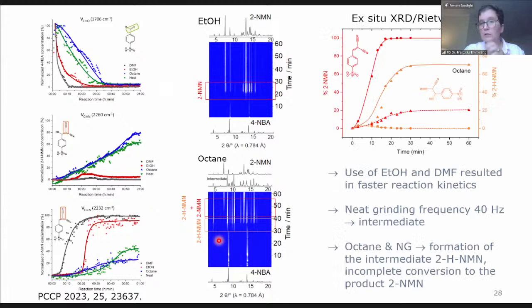We also then analyzed the data a bit in more detail using ex situ data and Rietveld refinement. And you see again, here we have the complete formation of the product in case of ethanol, and here using octane, we stop at a certain conversion, or the conversion is not complete within the time frame of 60 minutes.